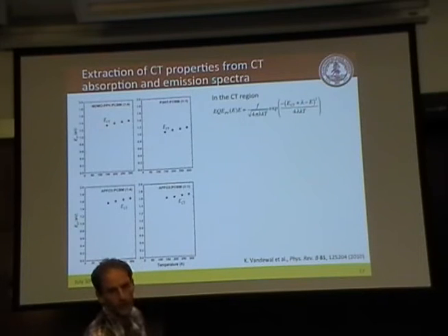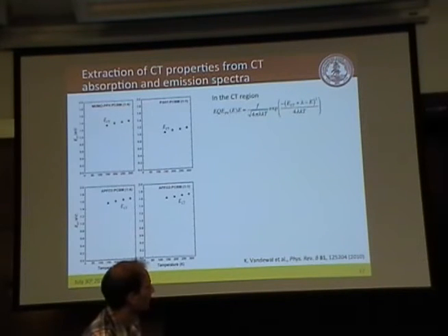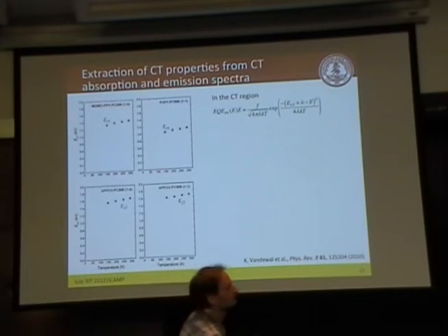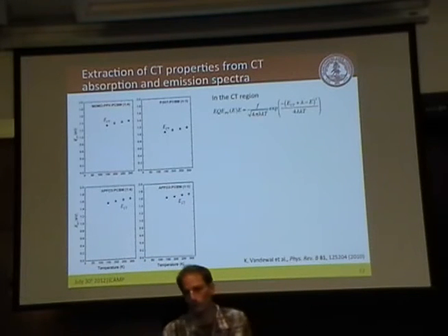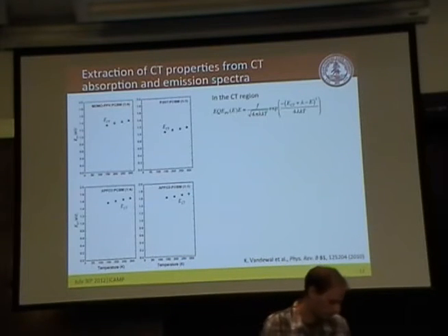We take these highly sensitive EQE spectra, look at this little Gaussian, fit our Gaussian formula to it, and determine like this the energy of the CT state. It's a bit temperature dependent. It might be due to disorder. We don't know why. I mean, also the optical gap of silicon is temperature dependent. This is not really normal.